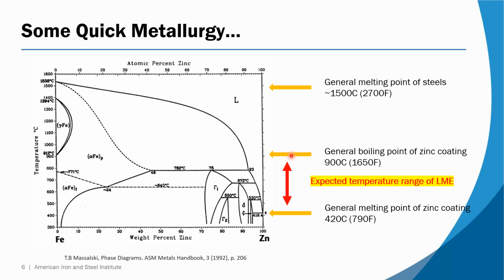However, there is one thing in our favor, and that's the boiling point of zinc, which is around 900 C. So you don't tend to see liquid metal embrittlement above 900 C because it just disappears, unless it's trapped in, like underneath the electrode - there's no air, it's a high pressure area, so you might have zinc there. But anything open to the surface would be gone by the time you get to the neighborhood of 900 C. So our general zone of concern is from 400 to 900.